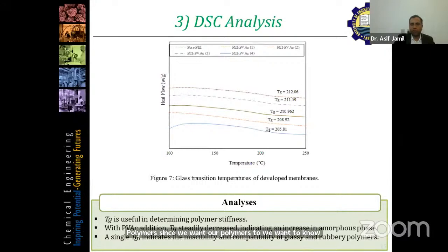So for example, first of all, the glass transition temperature for polyetherimide is 212 degrees Celsius, and it gradually decreases as you increase the concentration of polyvinyl acetate. For example, we have a single glass transition temperature here, which shows that our polymers are compatible.